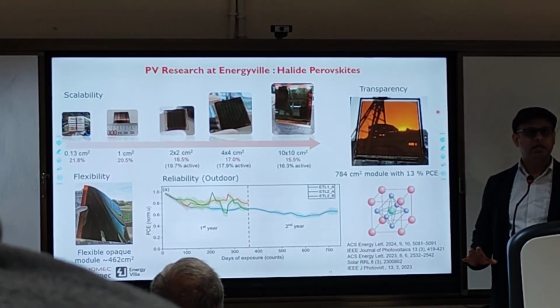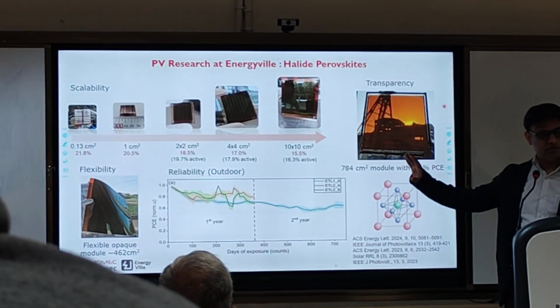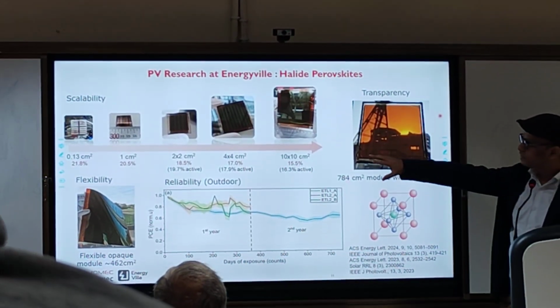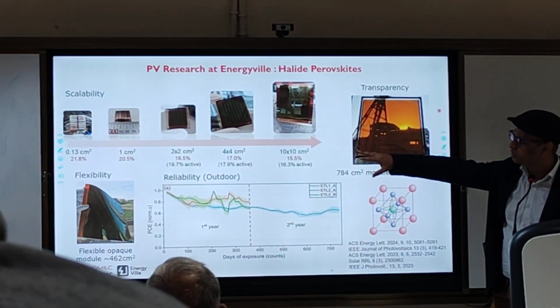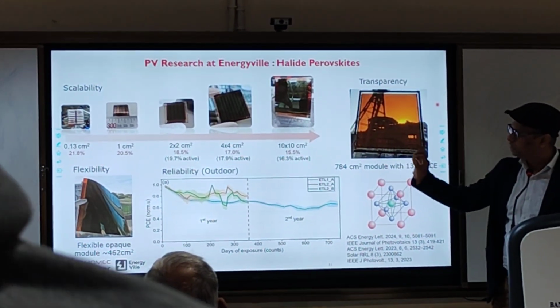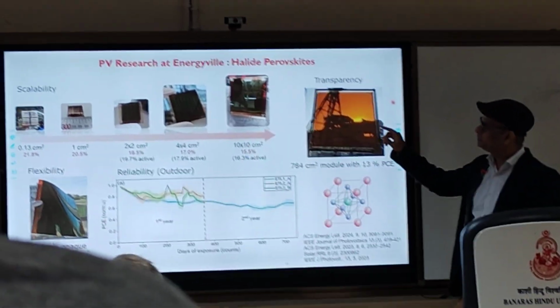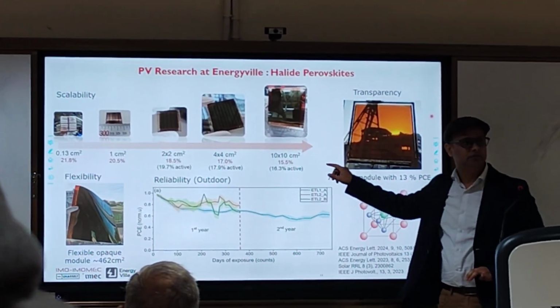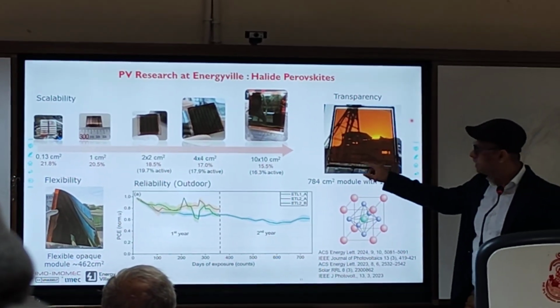Just pictorially, I want to show you what we do in our lab. These are halide perovskite cells. We started with very small cells, as you can see, 0.13 cm², a very small area, with very high efficiency, 21%, more than 20%. Then we scaled up to 10 by 10, which is 100 square centimeters, and we're still maintaining efficiency of more than 15%.